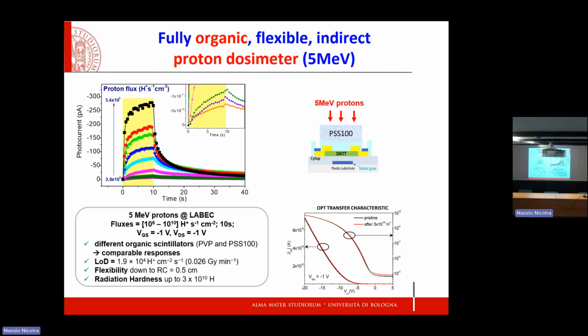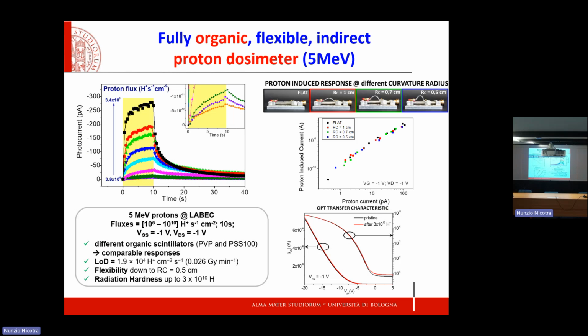Again, what happens under protons? This is the response of our device to 5 MeV protons. This is the response, in the yellow rectangle, under proton exposure, and the rest is the decay after the proton beam has been switched off. What is interesting is that the response scales nicely with the proton flux, so it is a dosimeter. And what is really nice is that the transfer characteristic of the organic phototransistor before, in black, and after, in red, multiple proton irradiations is not affected. So indeed, the scintillator absorbs all the protons and no damage is produced in the organic phototransistor, which can be nicely bent to various radiuses.